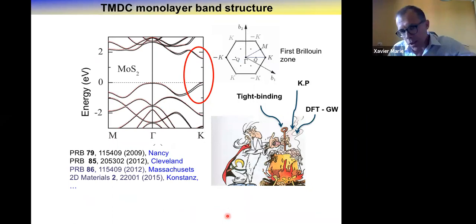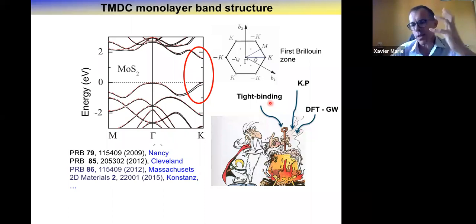And of course, in the past 10 years, a lot of work has been done in terms of band structure calculations to get information about the basic properties of these monolayers. So the approaches were basically using tight binding, huge work on ab initio approach, density functional theory, DFT, at different levels, more advanced level like GW, and also semi-empirical approach such as k.p. So all this band structure calculation confirmed that indeed you have a direct gap with electron state and hole states which coincide in reciprocal space, the minimum energy, but where they lie in the K valley.